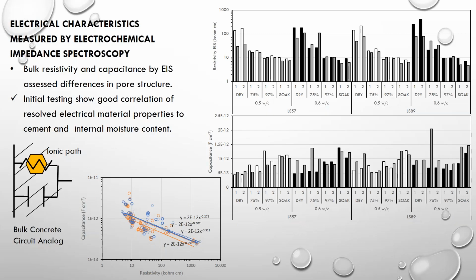And so the idea with EIS, we can identify the characteristics of concrete, including development of a resistive path and capacitive path that describes the solid parts of the microstructure of the concrete, as well as any moisture that's available in the system. So we have 2 fairly busy graphs on the right-hand side, the top one being the resistivity result from the EIS measurements, and we have our different rock size, limestone 57, 89, broken down to the water cement ratio and environmental content, and the same thing as well as the concrete capacitance, also broken down by the aggregate type, water cement ratio, and the moisture condition.